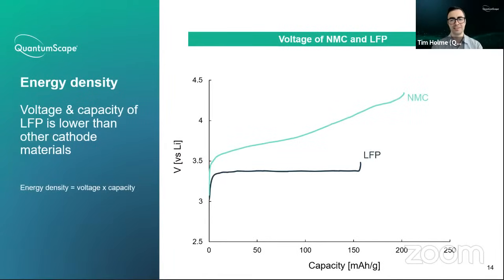However, as Sam also mentioned, the energy density of LFP is lower than NMC. And that really comes down to a product of voltage and capacity. Energy density is really the cell voltage times the cell specific capacity. If you look at the voltage curve of LFP as it's discharged, it has a capacity of around 150 milliamp hours per gram and a voltage down here. Whereas NMC, especially as you charge up to higher voltages, can have higher capacities and higher voltage. So the delta you're looking at is the area between these 2 curves, which gives a higher energy density for NMC based cathodes. And that's the reason why an NMC cathode will be prevalent in long-range electric vehicles on the road today.